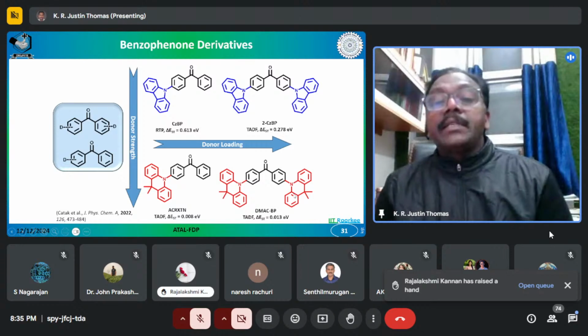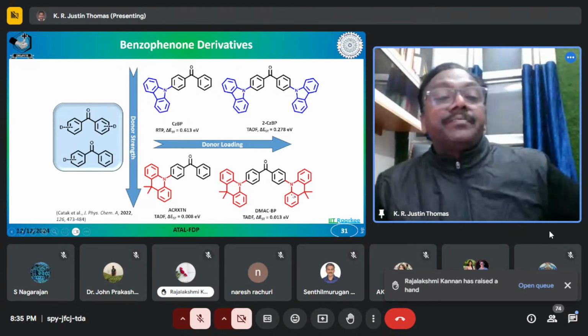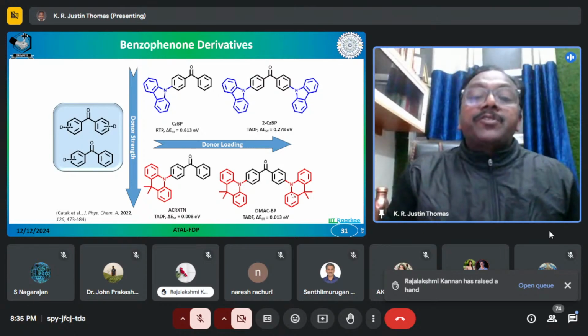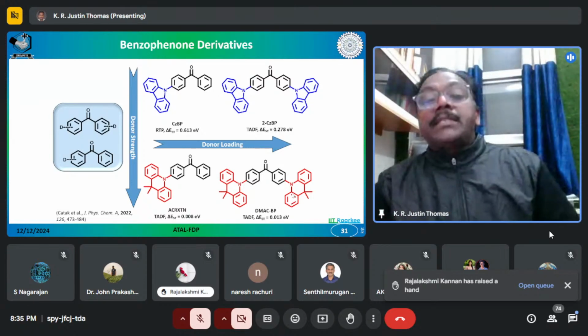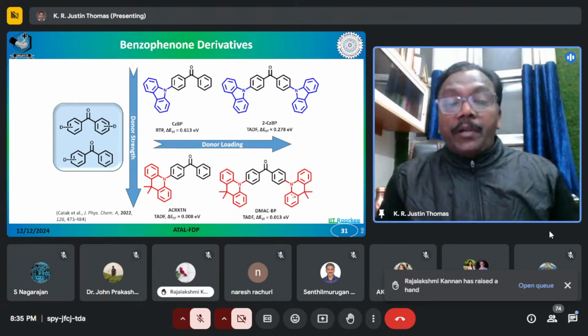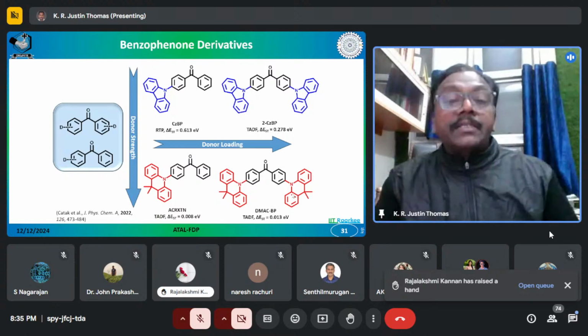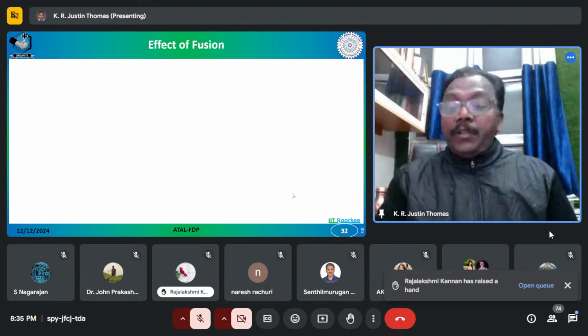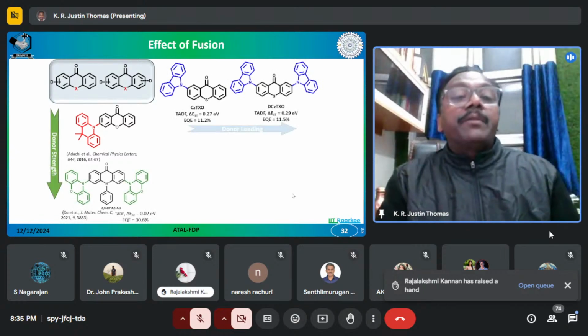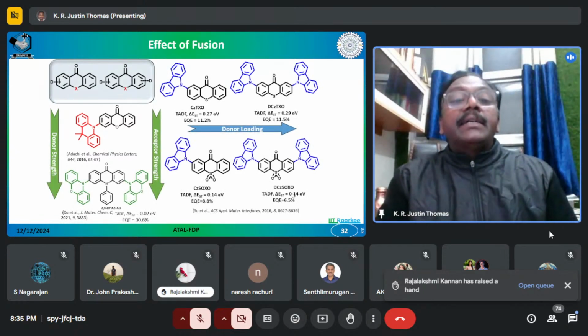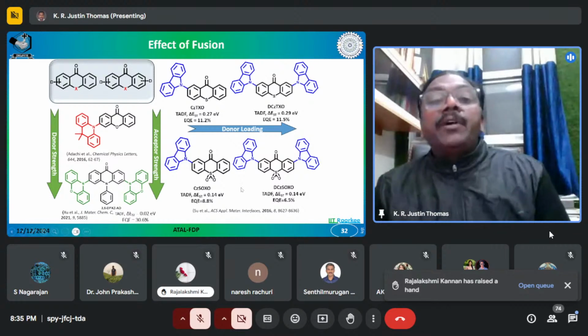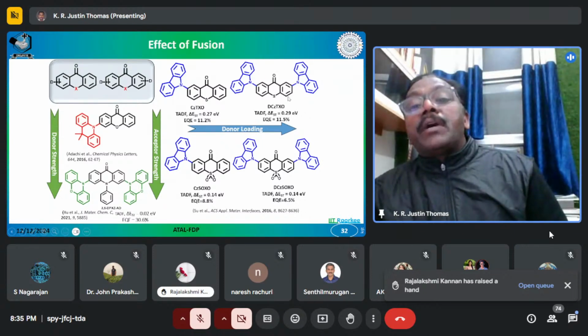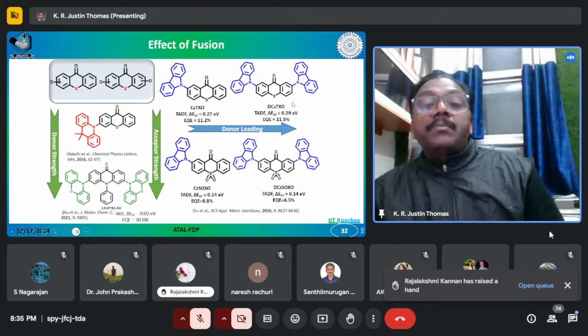And that makes the molecule TADF in nature. So you can see that by increasing the donor loading you can do this. This is the case with benzophenone. For benzophenone molecules, in order to realize TADF, you need to increase the donor loading, or you have to increase the donor strength. That is the lesson you are having from this. But when you have a fusion, as I have already told, you are going towards the fused molecules. You can see that the molecule now invariably becomes TADF, even when you are having one carbazole. Here you have a delta EST very close to 0.3 and it is a TADF molecule.